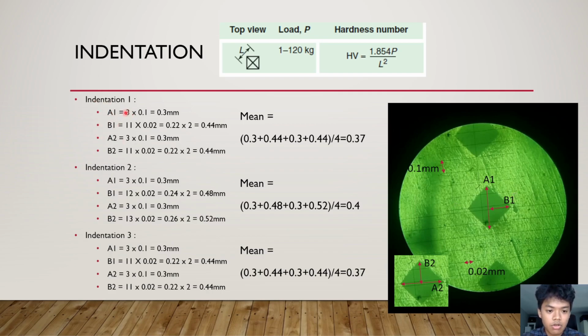We got A1 is 3 stripes, and we multiply that by 0.1 as shown here, and we get 0.3 millimeters. And for B, we get 11 from here to right about there. That is 11, and we multiply that by 0.02, and we get 0.22. And that's not the end of it. You have to multiply that by 2, because as you can see here, B is not all the way from end to end. B is only half the way, so you would have to multiply that by 2 to get the whole diagonal.